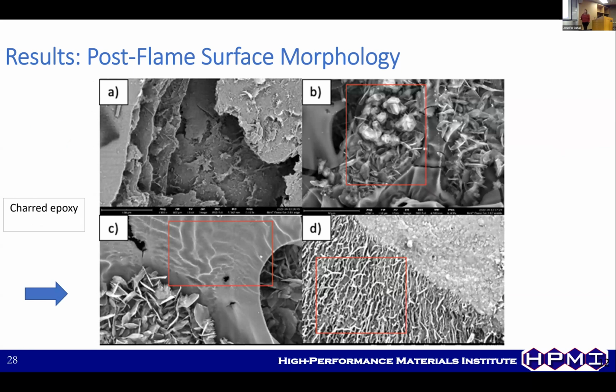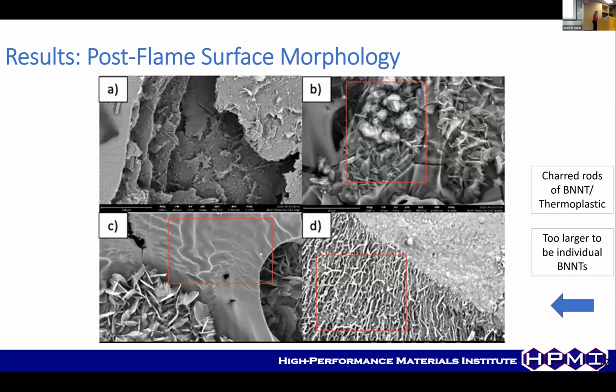And then we have some charred epoxy, with an asterisk to say this is likely thermoplastic. With epoxy and thermoplastic together, the epoxy likely would char off, but the thermoplastic would create this kind of veil. So this is likely the thermoplastic in the toughened epoxy that we have. So we have that charred epoxy that is really thermoplastic, and then we have charred rods of potentially BNNT thermoplastic.